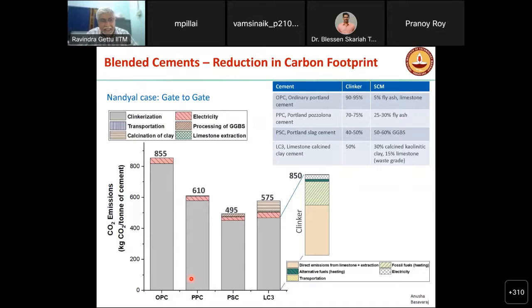And again, for this particular case of the cement plant in Nandyal, you can see in the chart below what are my carbon footprints for the different types of cements. OPC, as I said, most of the problem is due to clinkerization, 850 kg of CO2 per ton of cement. This comes down in PPC, Portland Pozzolana cement. On the table at the top, you see the different values that we have for the composition. Portland slag cement is much less.